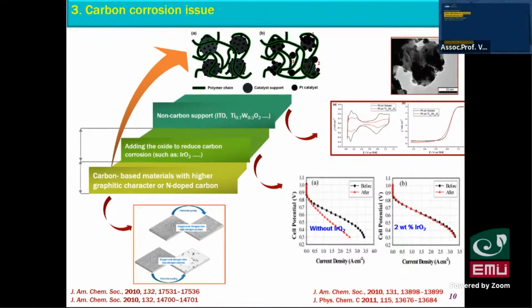The third approach people try is to address the carbon corrosion issue. As I mentioned from the beginning, the carbon gets oxidized during long-term fuel cell operation. So they try to modify the carbon, like carbon support materials with higher graphitic character, doping in nitrogen and other dopants into carbon, and also adding oxides to reduce carbon corrosion, such as iridium oxide. This is some of the result from previous research.